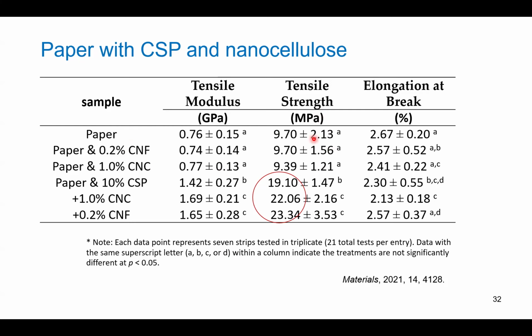And this paper by itself has a tensile strength of 9.7. If you just add the nanocellulose to the paper, it hardly changes. However, if I were to add 10% cottonseed protein to the paper, you see it doubled. You have doubled the tensile strength of paper, so giving value to the paper. And if you add, on top of the cottonseed protein, the nanocellulose crystals and the fibers, you can see you add an additional boost to the tensile strength, indicating indeed that both the cottonseed protein and the nanocellulose fiber and crystals from the cotton gin molds can add value to this material. So here is a case where we can convert potential microplastics into a value-added product.